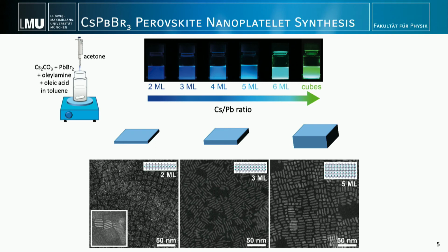So in the inset on the left and in the second and third picture, you actually see those platelets standing on their edges. So we could then measure their thickness, and we saw that we have multiples of the 0.6 nanometers, which we mentioned before. So we have, for example, here shown 2, 3, or 5 monolayer samples.